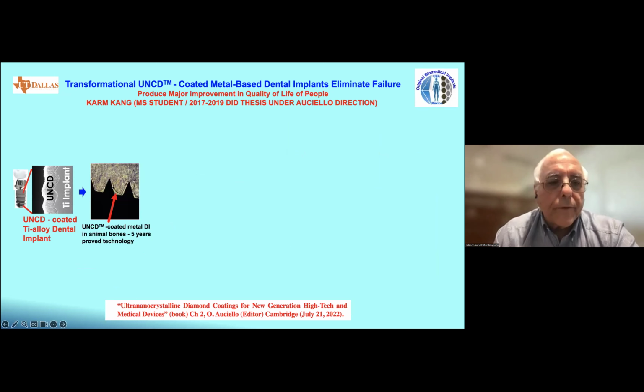So what we did, 5 years of animal studies with our colleagues at the University of Buenos Aires, Argentina. And we coated the commercial titanium alloys with our UNCD, as shown here on the left. And what we found is that it cannot be attacked at all by the oral fluids. And most importantly, the cells from the maxillary bone grow with high uniformity and with much higher density than on the metal.